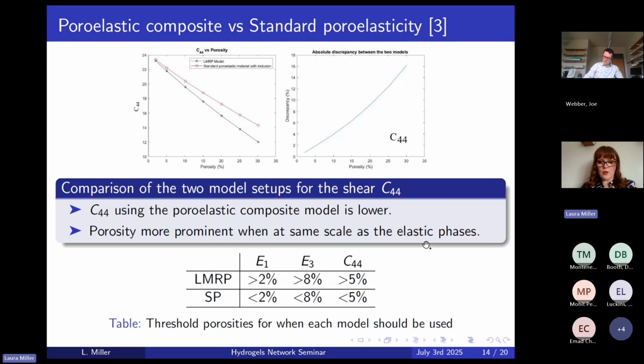So what we came up with was some threshold porosities for when each model should be used. These are just three particular elastic parameters that I'm showing in this presentation. In the paper, we tested various other ones. We found that if the porosity in your material, your biological tissue sample, whatever material you're looking at, is less than 2%, then technically either model is going to give you basically the same result.